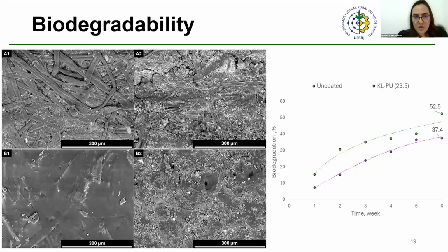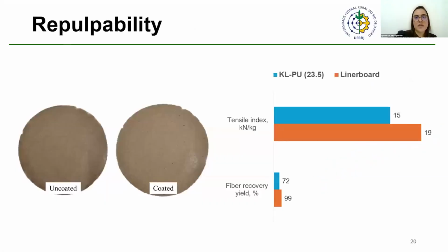And we see that the surface of the coated paper was degraded, indicating that the polymer coating that we applied is degrading in this environment. Both biodegradability and repulpability were evaluated using the sample with the highest coating grammage to simulate a more demanding barrier condition. To perform the repulpability test, coated and uncoated paper samples were repulped in water at around 50 degrees Celsius.